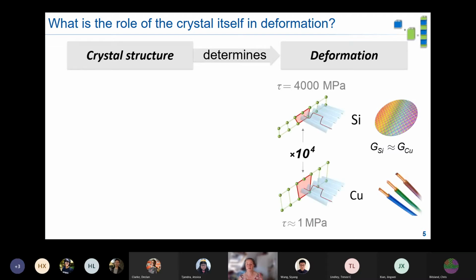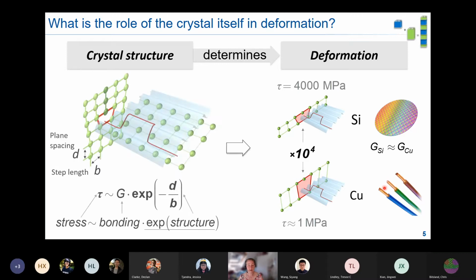And just to show you briefly that it is actually the crystal structure and not so much the elastic modulus or the bonding itself: if you compare two materials with a very similar shear modulus, like silicon and copper, then their intrinsic strength, so not after alloying and all of these things, differs by about 4 orders of magnitude. And the reason for that is that if a dislocation wants to move through the lattice, it has to overcome the resistance of the lattice.